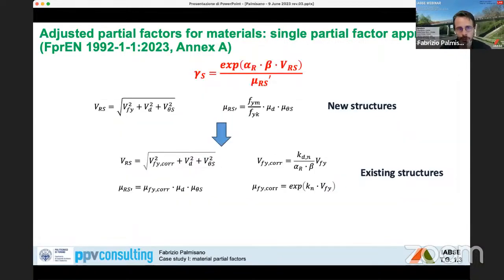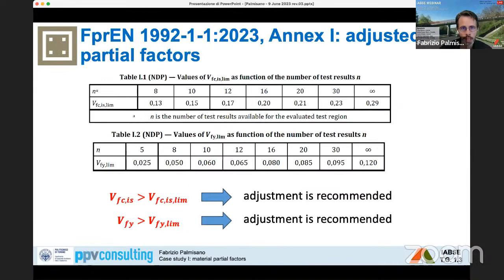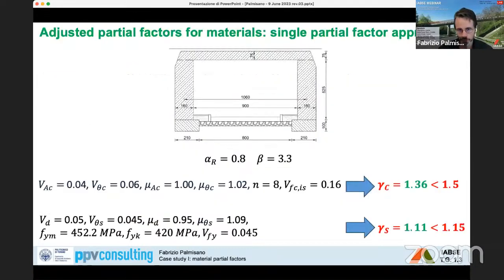The same expression is included in the forthcoming Eurocode 2 also for steel reinforcement. The only difference is that there is no difference between the in situ value and the value for a new structure for steel strength, but the formulation is the same with similar assumptions. It is worth mentioning that in Annex I of the forthcoming Eurocode, the partial factor adjustment will be recommended and not only permitted if the coefficient of variation for either concrete strength or steel reinforcement is greater than some limit value given by this annex, which is a function of the number of test results. Because in this case, we are not on the safe side anymore, as I have shown from the previous graph.